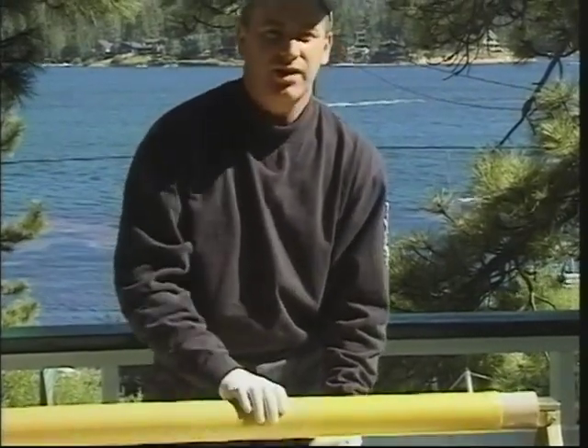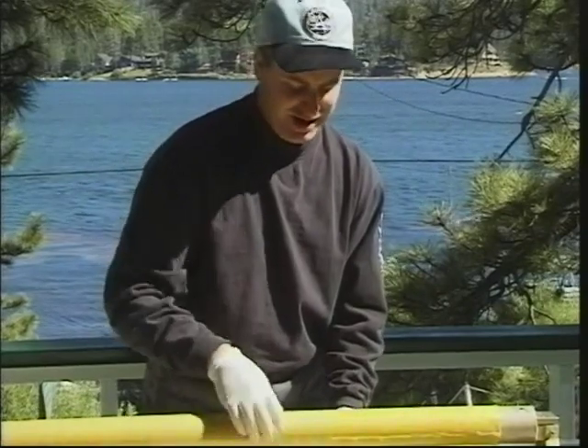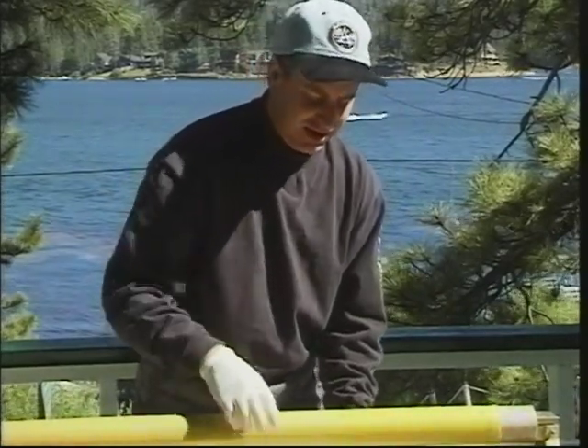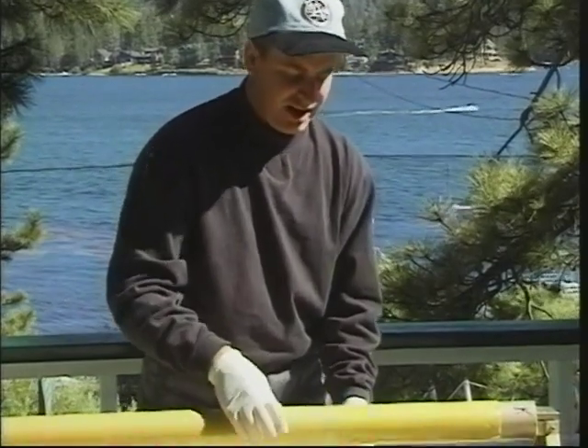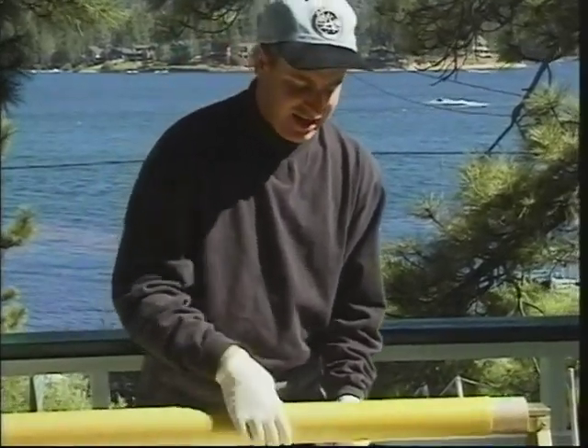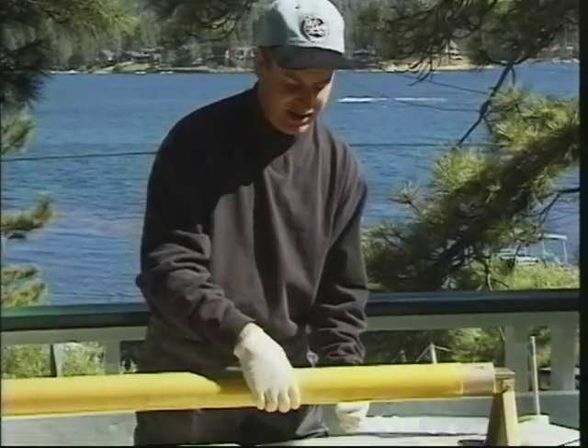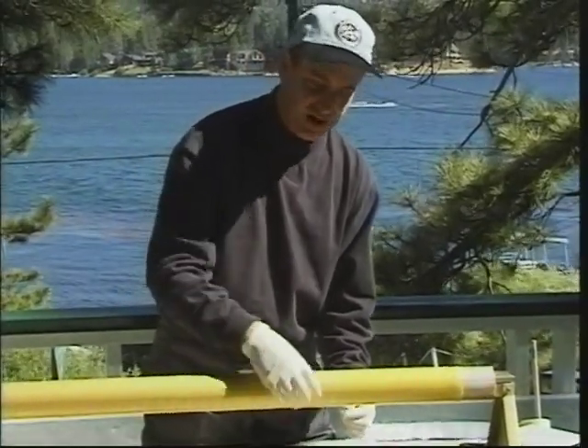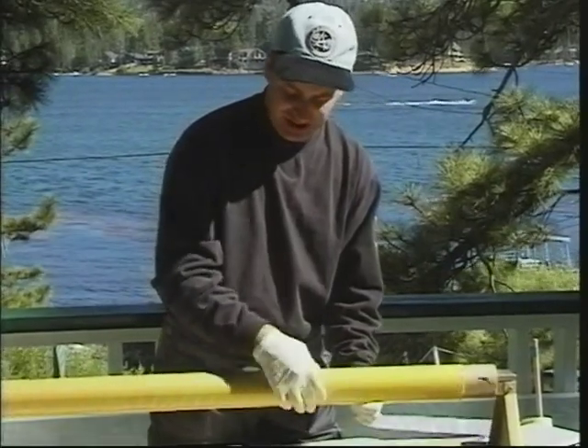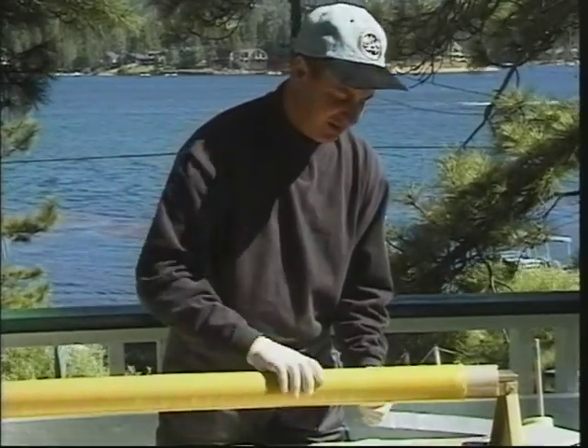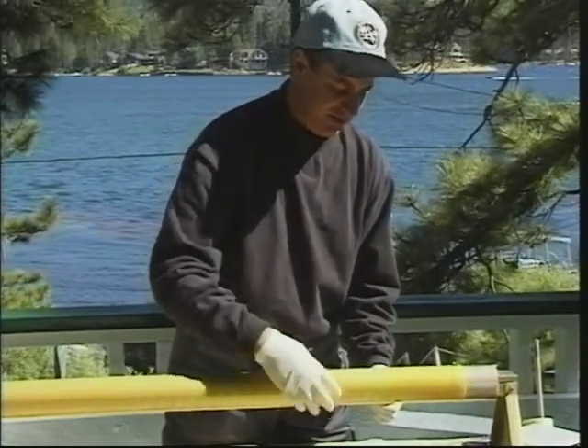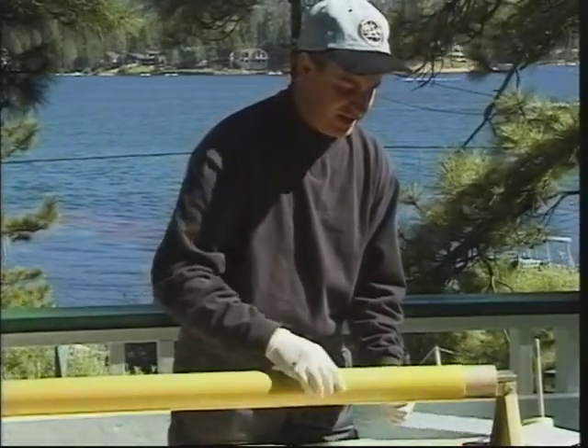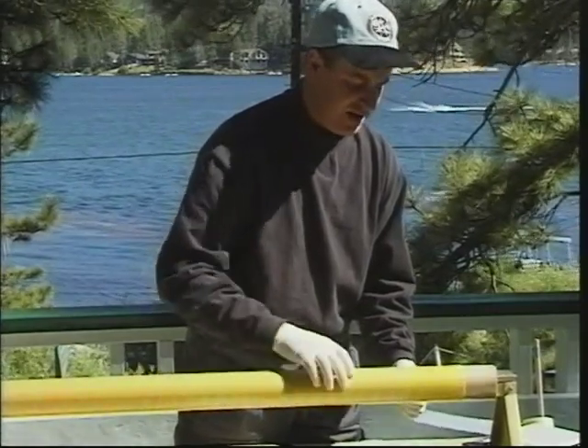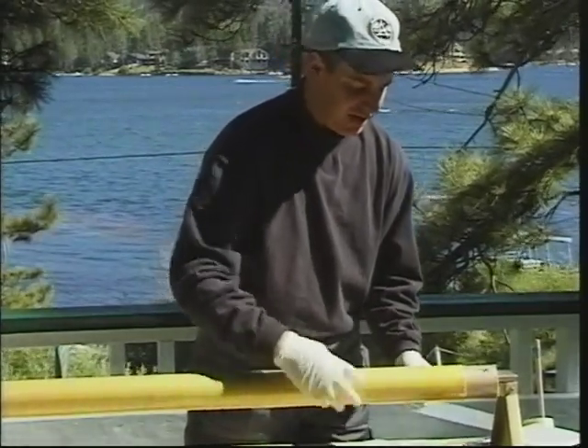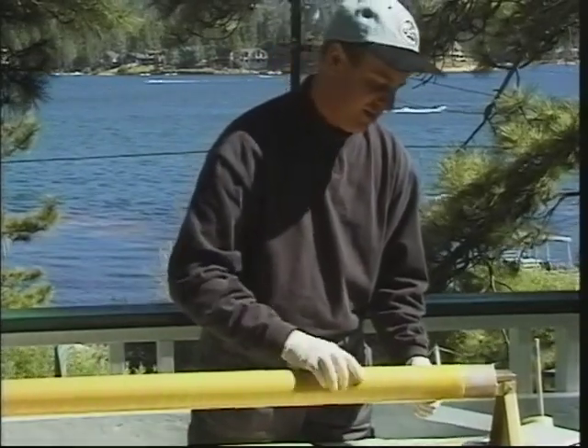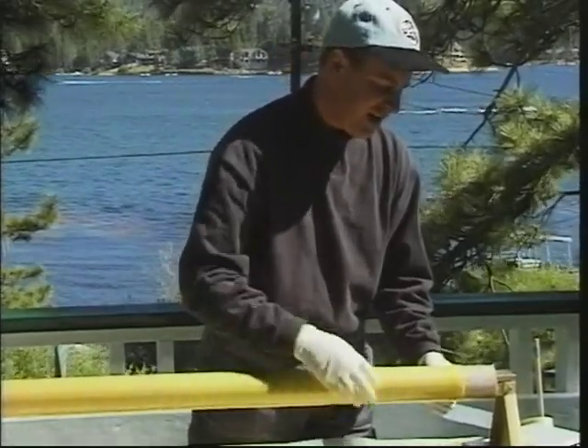If you do get an exceptionally sloppy winding technique and you still want to try to let it cure, what you can do is take a hair dryer and very lightly and carefully you can start the tape shrinking. So it'll start to get clean around the tube. Do it very carefully, please, because as you're heating this up, you're also going to be heating up the resin, and the resin will get very thin and run out of the laminate faster. So you've got to kind of play it by ear.